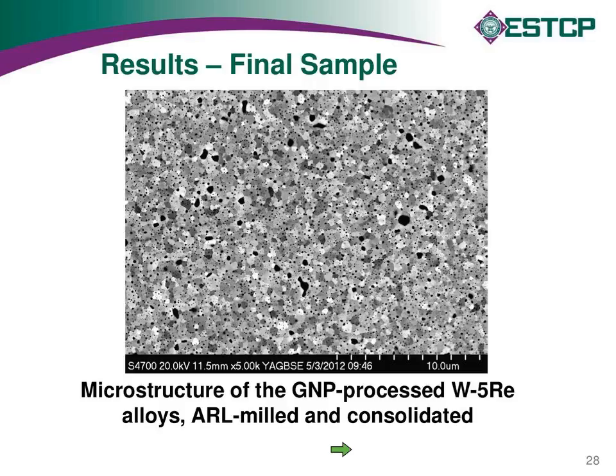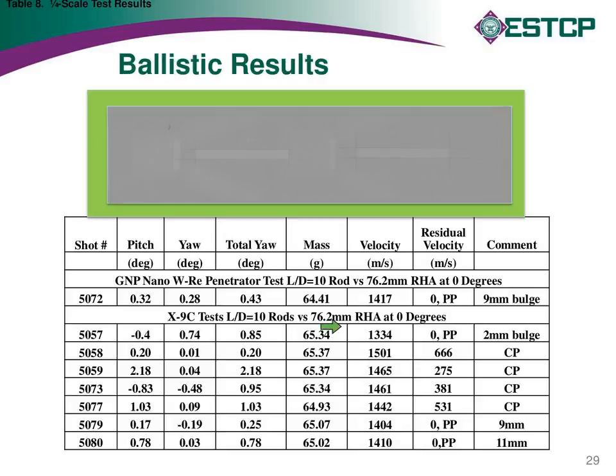We didn't have much material to work with, but we ended up making one ballistic penetrator. So we tried to make that shot count, and that's the result you're seeing here in the table on slide 29. I don't know if the contrast is good enough. This is the projectile flying. We have two images here in the X-ray. You can see the pusher plate in the launch package behind, and there's a plastic obturator you can maybe faintly see there. But you see it was a very good flyer.